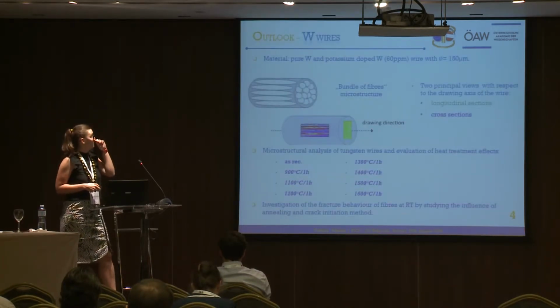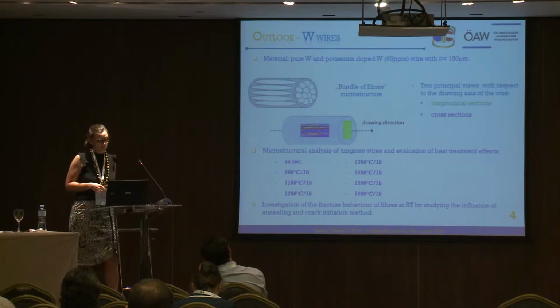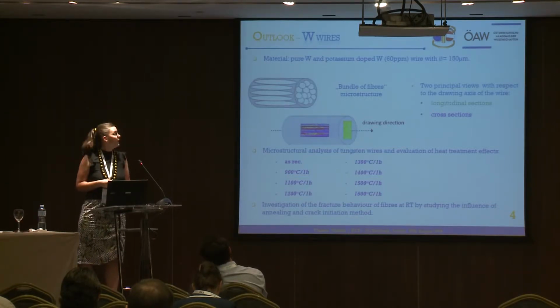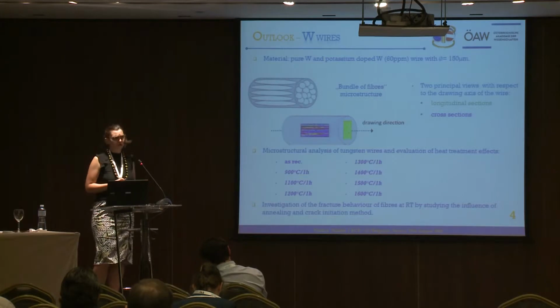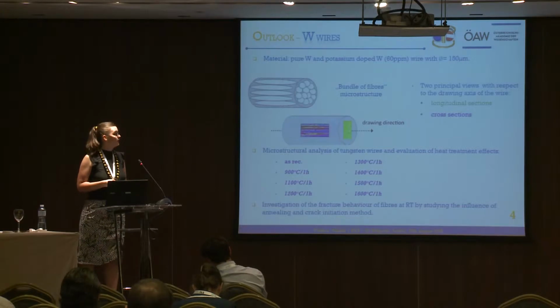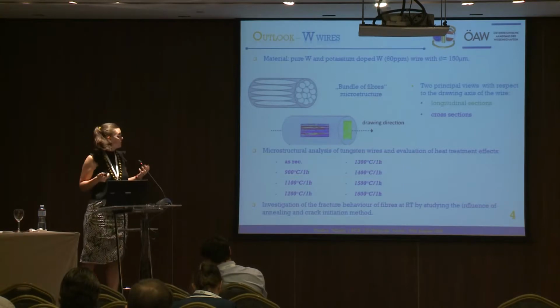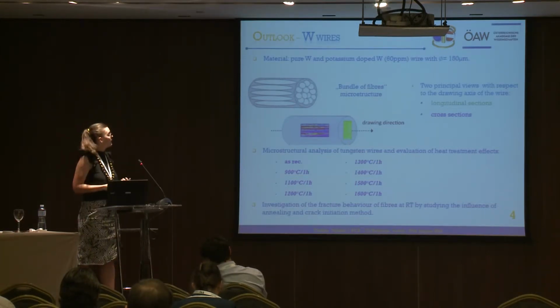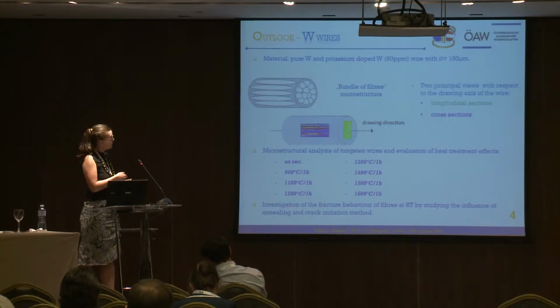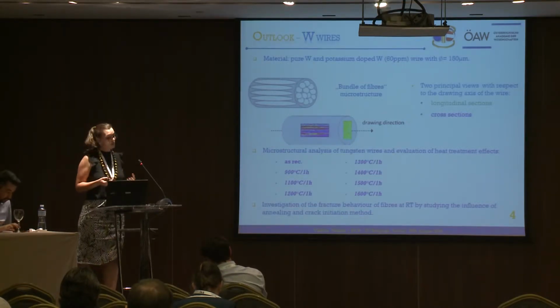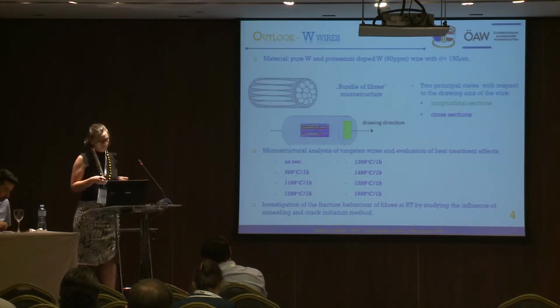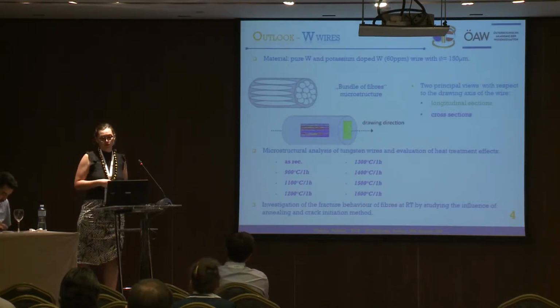Okay, so we were investigating two types of wires, namely pure and potassium doped wire. The diameter was 150 microns. The first part was, of course, microstructural characterization. These materials, during production, experience a very high degree of deformation, which has a very large influence on the resulting microstructure. In this case, we have something called a bundle of fibers microstructure, meaning a very elongated grain structure along the drawing axis.